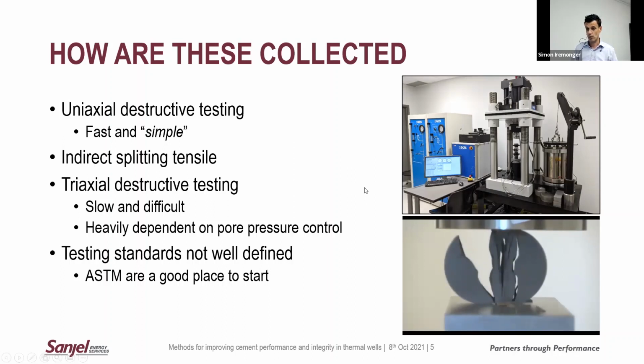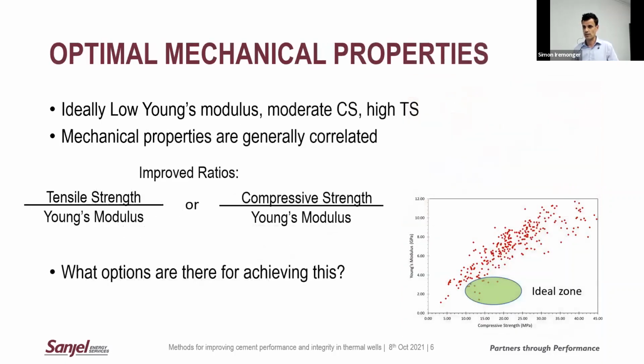So you can certainly do triaxial tests as well. Under real well conditions, you do have the three axes. You've got your confining pressure and your pore pressure as well. In a commercial lab like this, where we're trying to find the best value solutions, it's been pretty challenging because these tests are very, very slow and difficult to do. Typically, we're engineering these systems to have incredibly low permeability wherever possible. And this triaxial testing is heavily dependent on pore pressure control, so it can be difficult to get accurate results if you're going to be doing that. And just to add another challenge, the testing standards aren't particularly well defined for mechanical properties testing, especially in the oil and gas industry. And so we've always gone off your ASTM standards for the construction industry as a good place to start when you're developing and doing your own testing in situ.